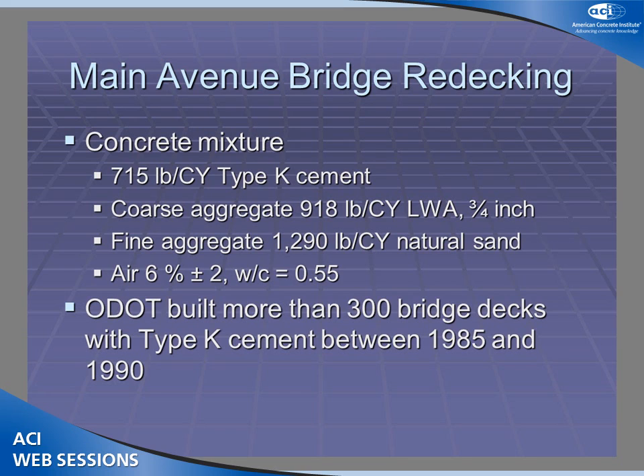Considering that they've gone probably a couple decades without any serious bridge deck cracking problems, you can see why they're even more concerned when they switched to HPC and had these problems. The coarse aggregate was 3/4 inch lightweight aggregate, air, relatively high water cementitious ratio of 0.55 with a fair amount of Type K cement.